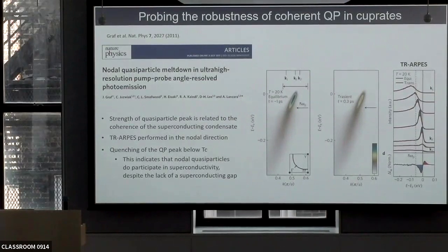Fabio: In our case, it happens below and above TC. We also did it on 2201, where TC is pretty low, and you can still see it. This was optimally doped 2212, so I think TC was 90 Kelvin. My question just referred to the sentence here about the connection between nodal quasi-particles. A superconductor has, of course, nodal quasi-particles. It's a d-wave, yeah.